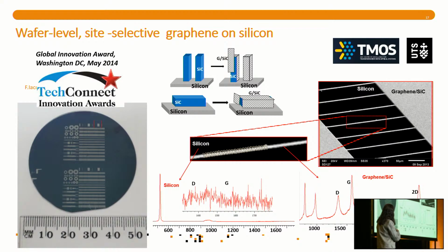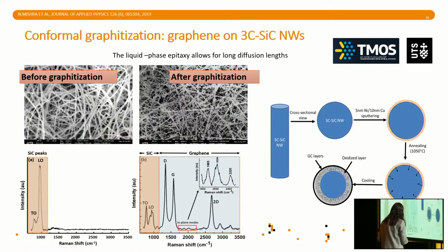These were MEMS, like bridges suspended on the silicon here. And you can clearly see that wherever this is colored in a light color, this is basically the part that is silicon carbide and graphene on top, and everywhere else is just silicon, so there's no carbon there. And the very interesting part of this is that you can do that directly at wafer level by pre-patterning the silicon carbide, and there is a very good chance to introduce this into semiconductor processes.